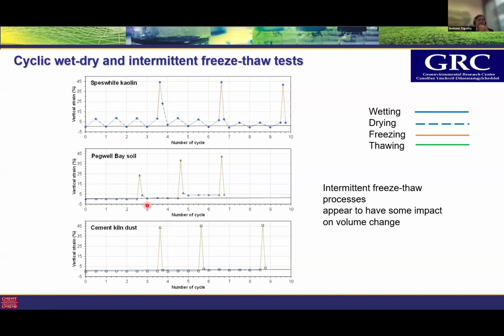As you can see, for Pegwell Bay soil and cement kiln dust, there is very little swelling and shrinkage, but they affected the frost heave and thaw settlement. In the case of Pegwell Bay soil, the frost heave increased with cycles, whereas in the case of cement kiln dust, there's a kind of stability. There is not much effect that wetting and drying had on the frost heave and thaw settlement.